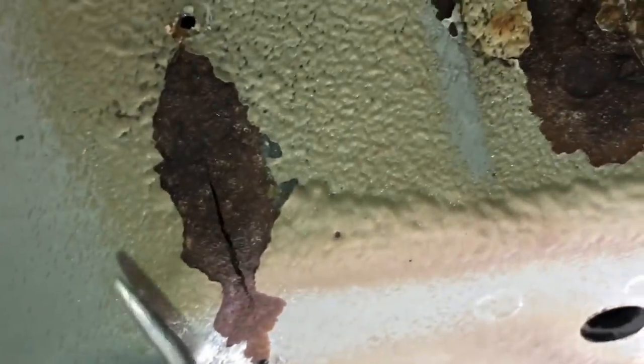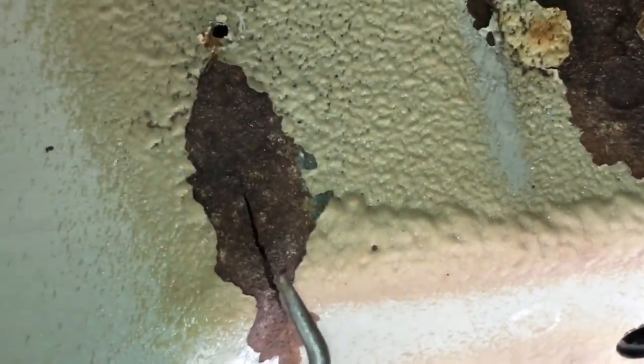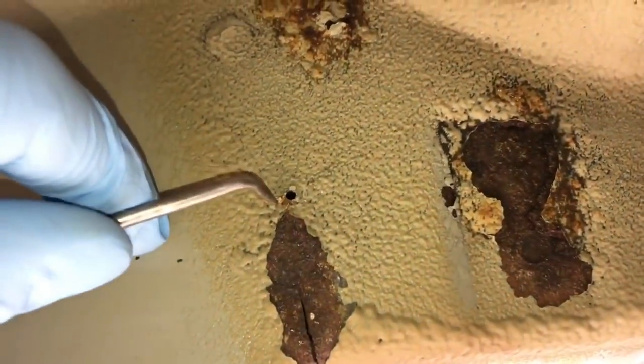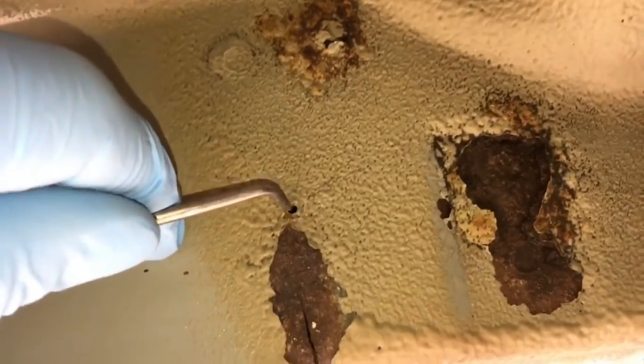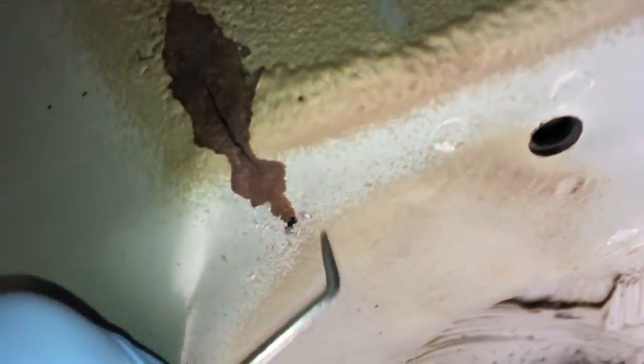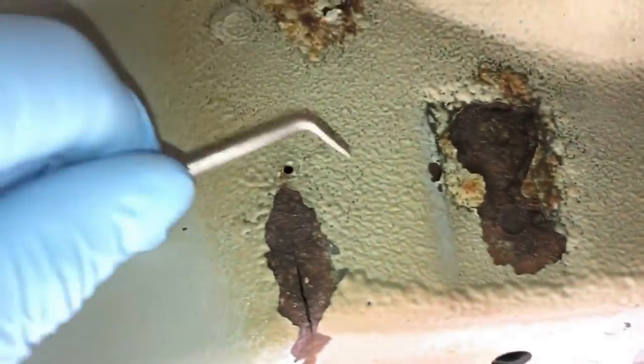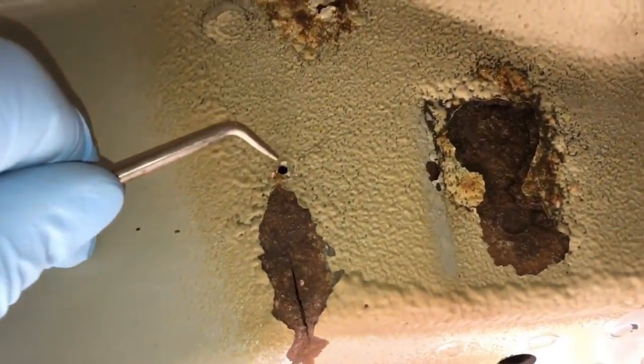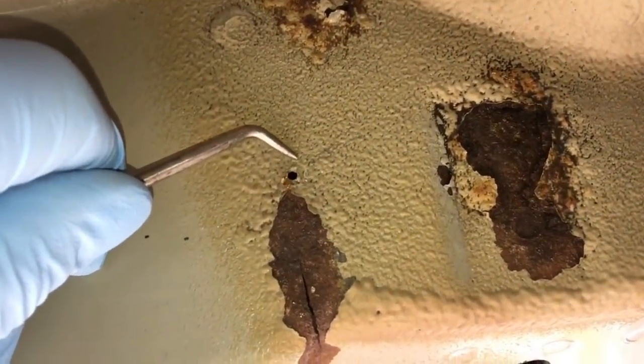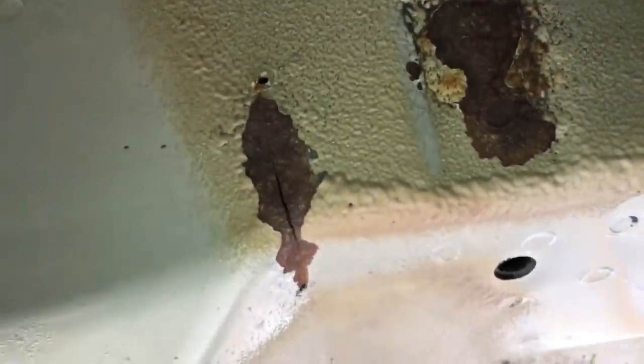This one's, interestingly, quite open. It's not very hairline anymore. It's actually a gap in there, so the corrosion is going through that panel, but the crack could be going further than the stop drill that we can see here. But now we've got a good indication of where we think it's finishing. Then we gently remove the seam sealer, and if it looks like there's a line going out further, then we'll simply do another stop drill as well to be absolutely 100% sure we've dead-ended the crack even before we start any welding work on those cracks.